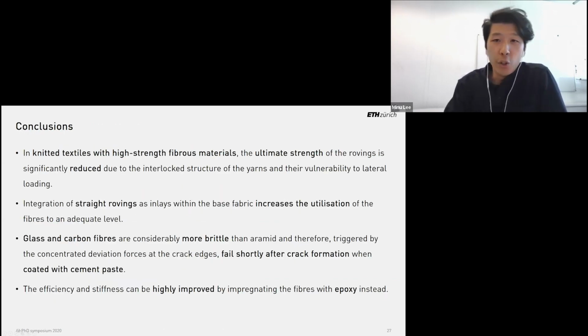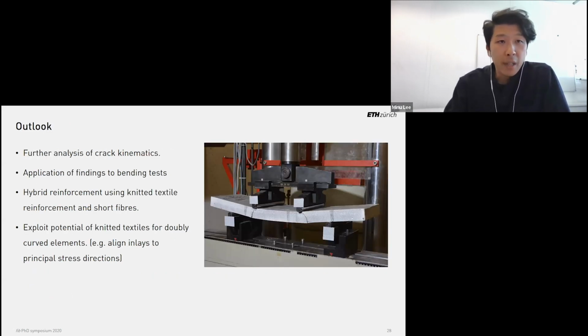So now coming to the conclusions, in knitted textiles with high strength fibrous materials, the ultimate strength of the roving is significantly reduced due to the interlock structure of the yarns and their vulnerability to lateral loading. The integration of straight rovings helped both in strength and stiffness, although it really depends on the type of coating. So with cement paste, the glass and carbon fibers failed shortly after cracking, but with epoxy resin, we could improve both strength and stiffness.